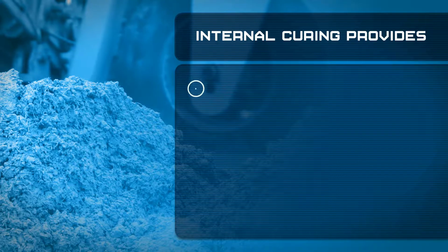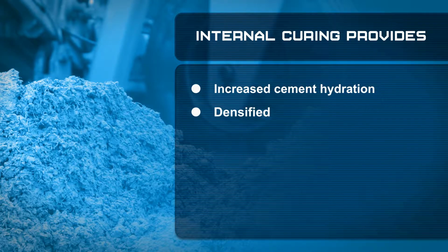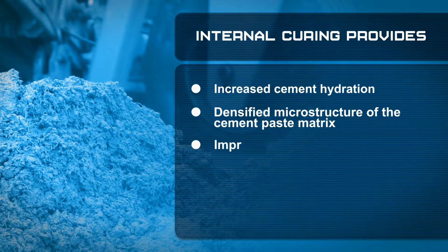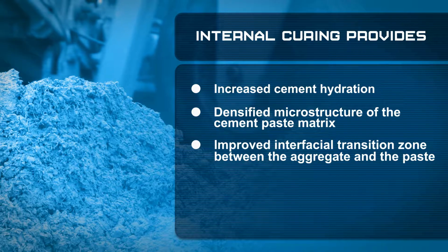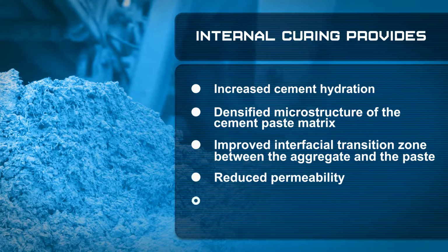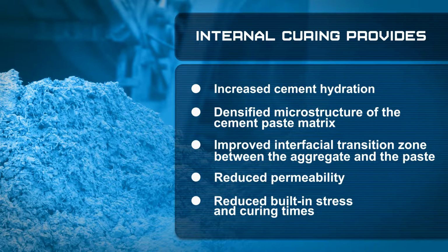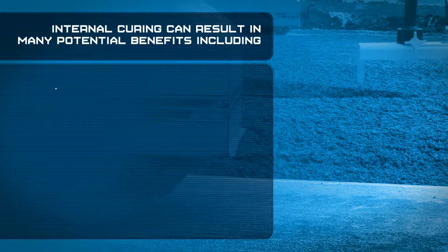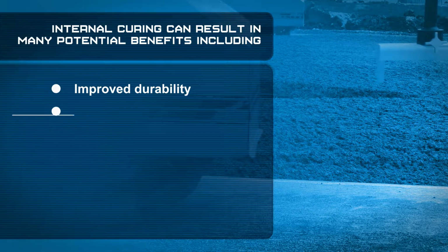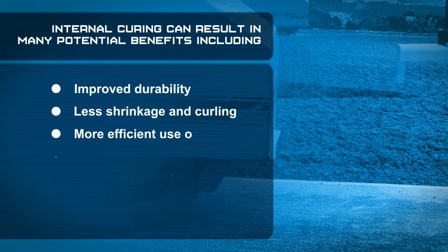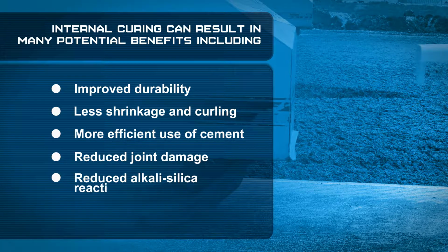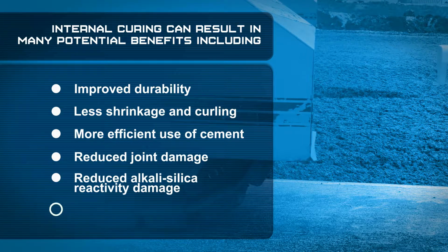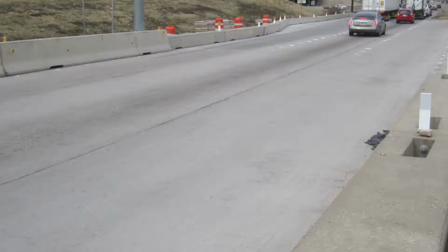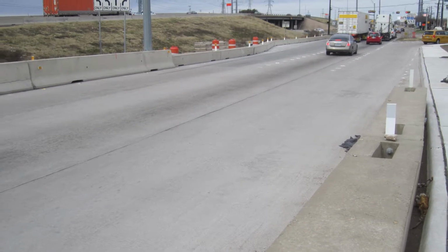Internal curing provides increased cement hydration, densified microstructure of the cement paste matrix, improved interfacial transition zone between the aggregate and the paste, reduced permeability, and reduced built-in stress and curing times. These changes can result in many potential benefits, including improved durability, less shrinkage and curling, more efficient use of the cement, reduced joint damage, reduced alkali silica reactivity damage, improved fatigue resistance. Ultimately, internal curing results in fewer and tighter cracks. Increased strength and durability results in a longer service life and lower maintenance costs over the life of the pavement.